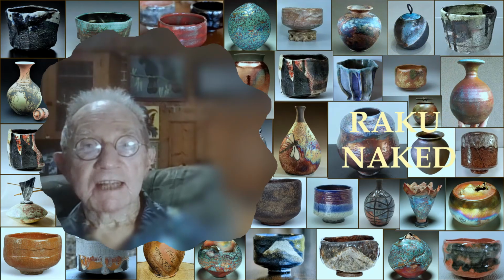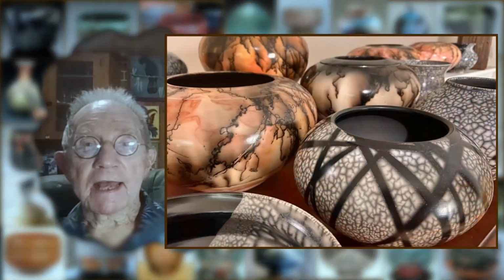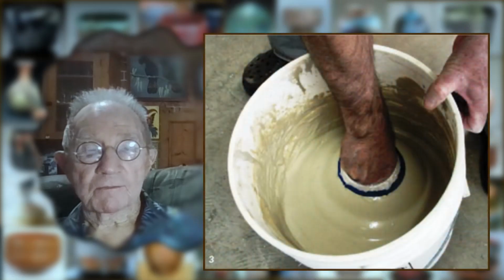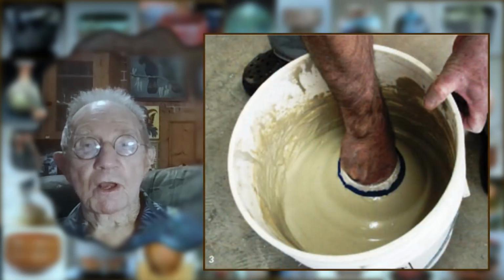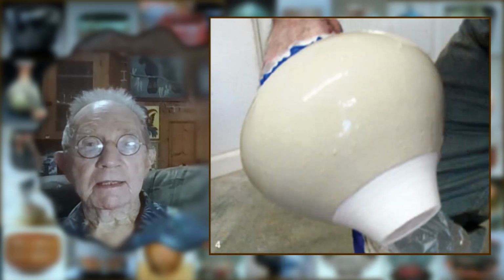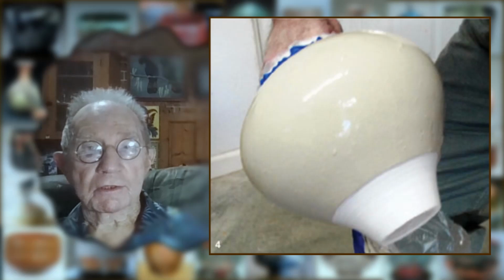There is another form of raku firing which has the rather racy name of naked raku. It differs from the method already described for a couple of reasons. The naked part refers to the fact that there is no glaze involved in this method. There are two different processes. In the first one, the bisque pots are coated with a thick slip and refired. During the firing, the slip will crack or craze, but it does not adhere to the pot.